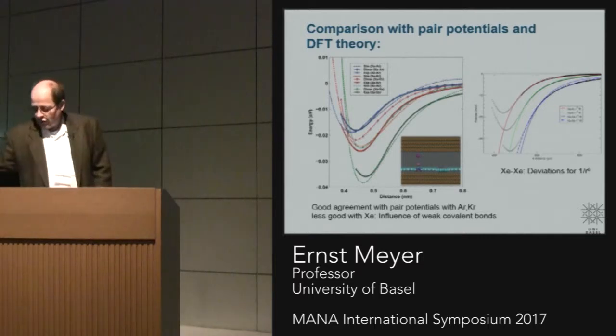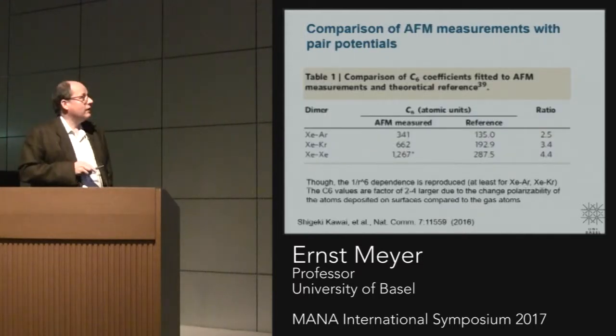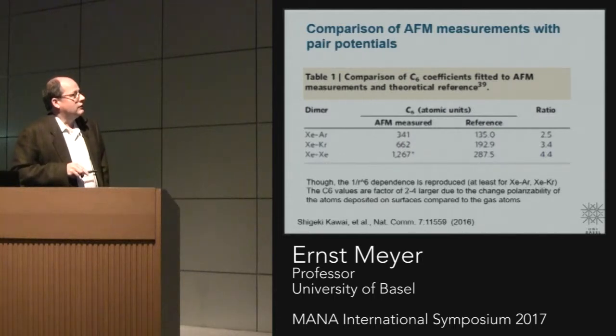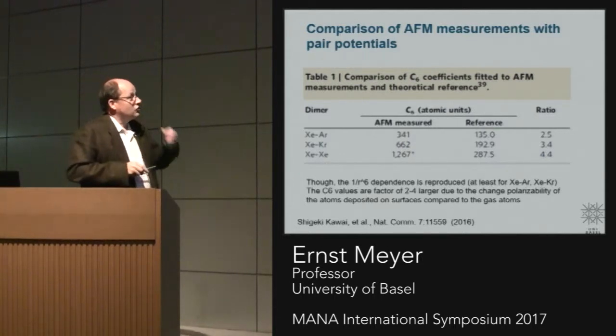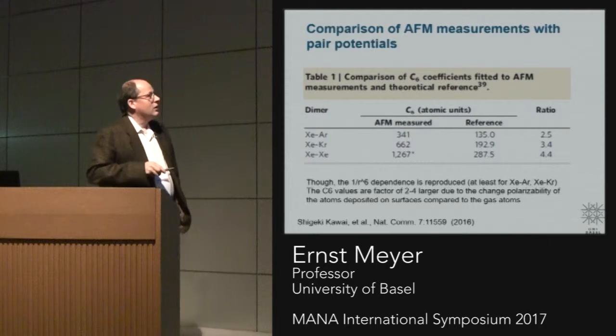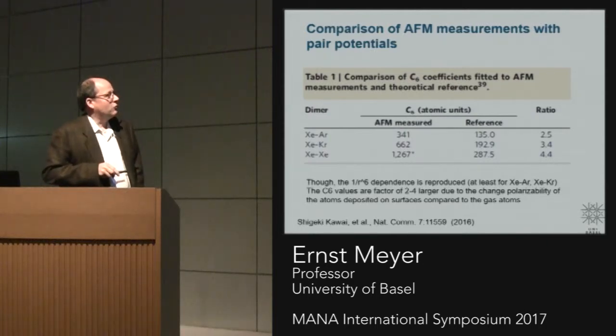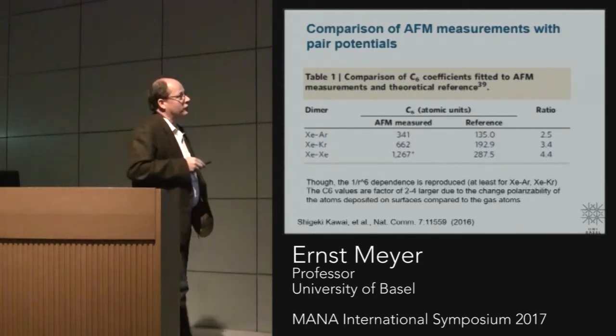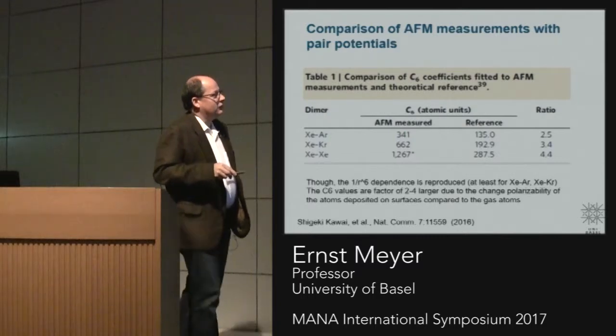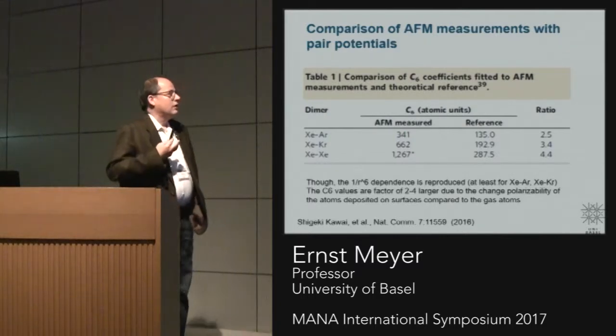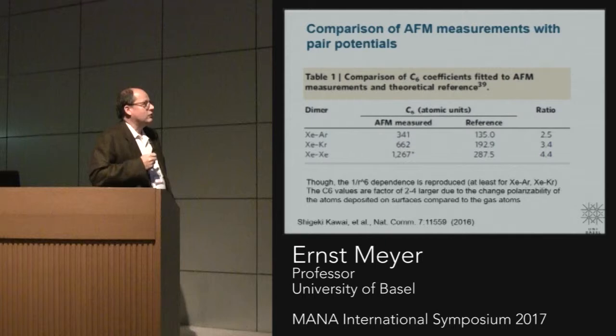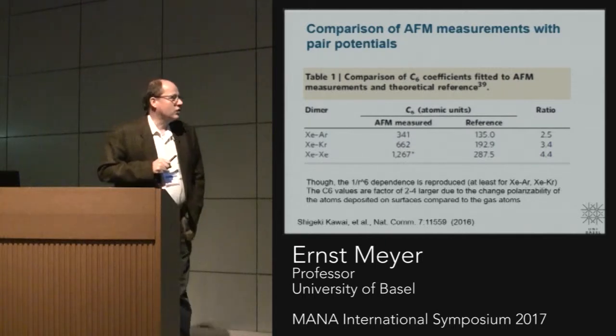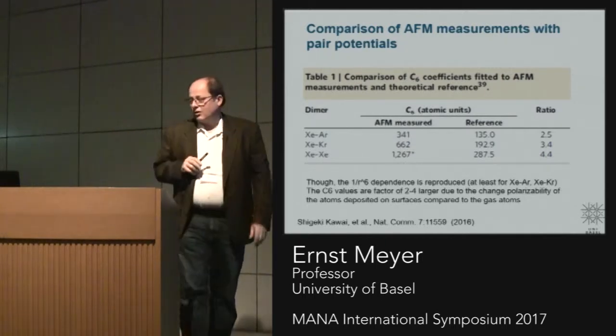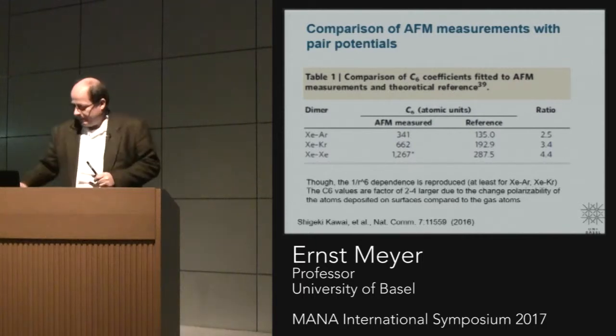And if you look in a bit more detail, we see that the C6, this coefficient from the power law, is quite different from the normal pair potential from gases. We have a factor of 2 to 4 here. So it also means that the polarizability of the atoms is really changed by being close to the surface.